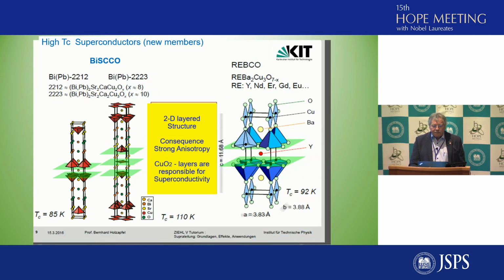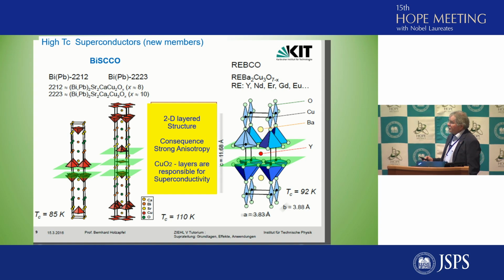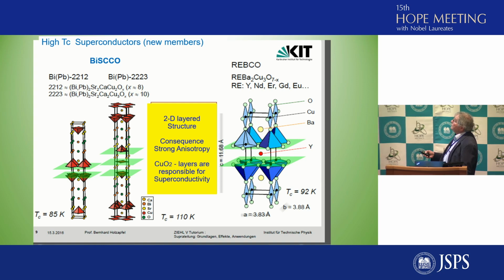So this is an example of the series of new materials, 2 groups, bismuth-based compounds, copper oxide, and yttrium or rare earth-based compounds. They are all 2-dimensional structures. They are layered structures, and this has a consequence for the physical properties because they show strong anisotropy.